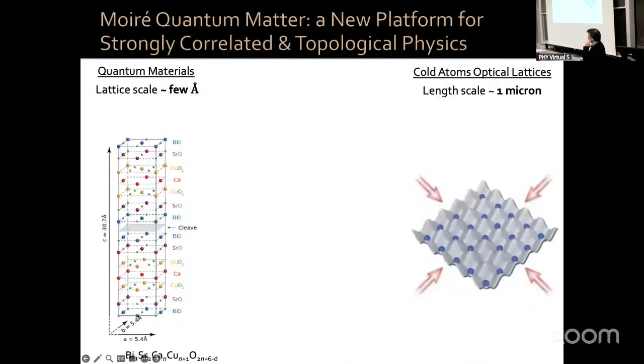So we have traditionally these two platforms to study strongly correlated physics and topological physics. One is just usual quantum materials that we've been exploring for 100 years or so, where the lattice scale is of the order of a few angstroms. This is a picture of a high temperature cuprate superconductor, for example. Here we have thousands of these materials. But if you take just a particular crystal, you have relatively little control over the properties of that crystal in terms of changing its behavior. If you want a different behavior, typically you have to grow a different crystal with a different chemical composition, with a different disorder realization, etc.